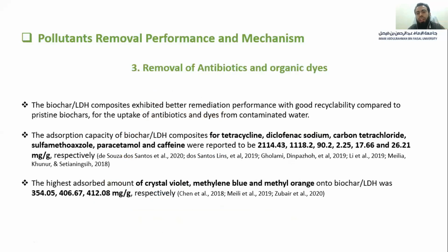Similarly, they also showed very high removal performance and reusability performance for different types of pharmaceutical emerging pollutants. And you can see here in the second line, for different types of pollutants: tetracycline, diclofenac sodium, carbon tetrachloride, sulfamethoxazole. These are the antibiotics which are used for different applications. So the LDH biochar composite showed high removal performance, greater than 2000 milligram per gram from the water. Even for the dyes like crystal violet, methylene blue, methyl orange, the removal capacity is greater than 300 milligram per gram.